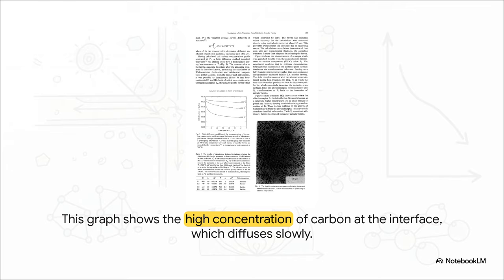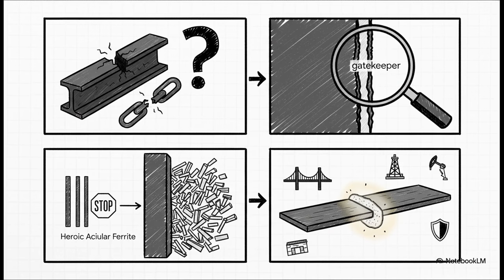So the gatekeeper doesn't just physically block the boundary, it creates a chemical force field, a carbon wall, that makes it impossible for Bainite to even get started. That is the real secret to its power. So, to wrap this all up, we've gone from a dangerous puzzle to a really profound understanding. The paradox of stronger alloys making weaker welds was solved by discovering the role of this humble little gatekeeper layer of ferrite. This layer builds a chemical carbon wall that blocks brittle structures and lets the tough ones grow.